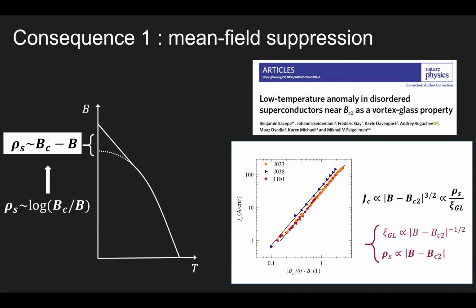We looked at the critical current as a function of temperature, as a function of magnetic field here. And in this paper, we found a very unusual scaling. Actually, it was not unusual, but we found a scaling of the critical current as 3/2, which is actually the same as we expect close to TC. But this is the scaling you expect for depairing critical current in a mean field transition. And if you believe that you can have the same mean field behavior here, you expect, therefore, to have a superfluid density that scales linearly with the magnetic field. And these measurements that I showed you of superfluid density are a beautiful confirmation of this mean field behavior and explain why the critical current goes with an exponent 3/2.